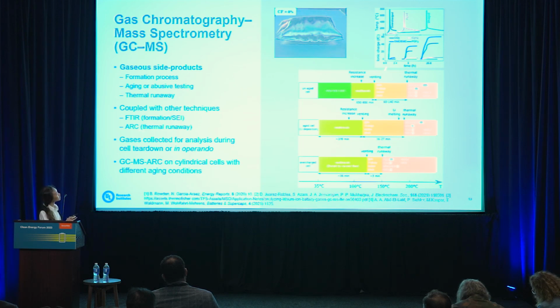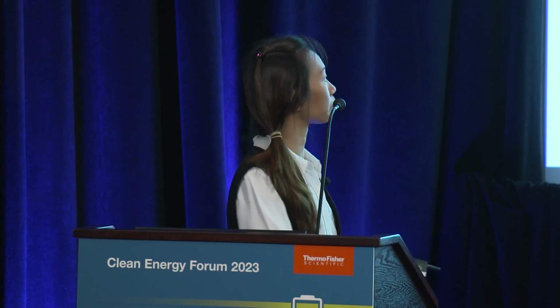On the right here is some data from a study on cylindrical cells with different aging conditions, and you can see the overcharged, aged, and unaged cell. You can see that at different times, different gases are released and different amounts of gases are released. That way we can understand how safe the battery is when it goes into thermal runaway, and what the gases are that are produced.